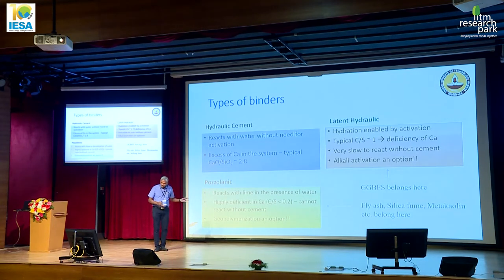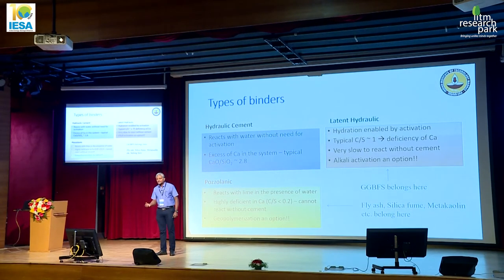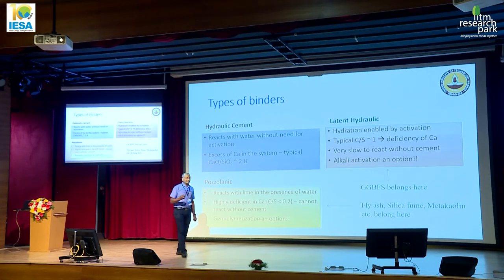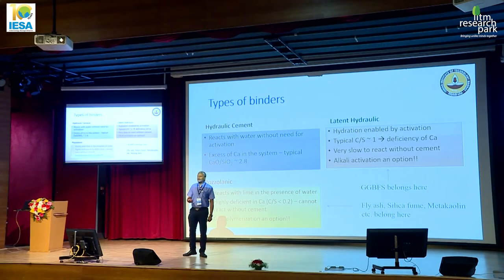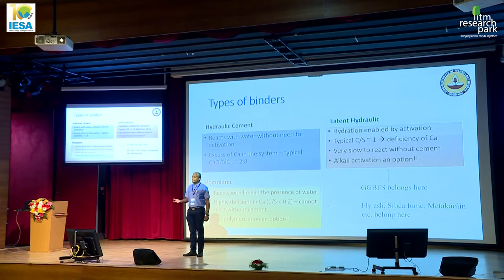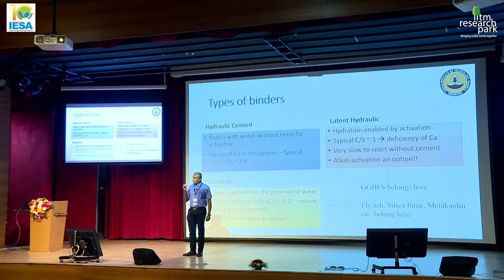Now, of course, there's a little bit of chemistry here. Calcium-rich supplementary materials fall under the category of hydraulic cements. They can react with water on their own. But slag cannot react with water on its own. It needs some activation, generally by alkalis or sulfates. Fly ash, on the other hand, whatever you do, cannot react on its own.